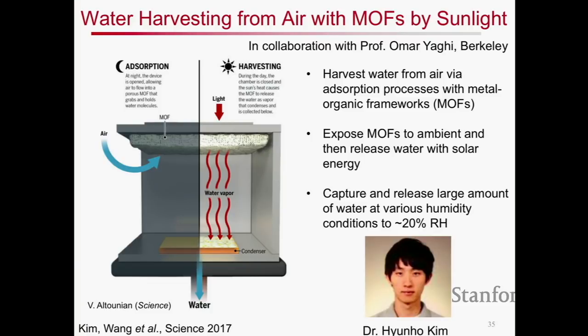And because of the unique properties, as I'll get more into about these MOFs, you can release the water relatively easily if you apply a small amount of heat. So you can apply sunlight in the form of heat to release these water molecules that are adsorbed onto this material, and now form locally an environment that has relatively high humidity, nearly 100%, such that you can condense this water near ambient conditions, right? So you don't actually have to use refrigeration to allow for this water harvesting. And so the key here is, of course, the material set.